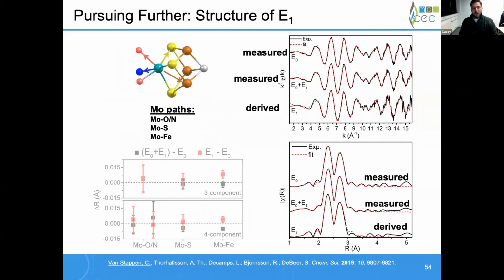If we go back to molybdenum really quick and fit these scattering paths, I want to mention that we're actually measuring the E0 sample and this mixture of E0 and E1, as Yulia pointed to earlier. And so when I'm talking about this E1 spectrum, it's actually been derived from the other two by subtraction. Now, with that in mind, it means that I have two data points I can fit to see if I have any trends and changes in distances. And it's important that whatever I find from my derived E1 spectrum is also supported by the E0 plus E1.